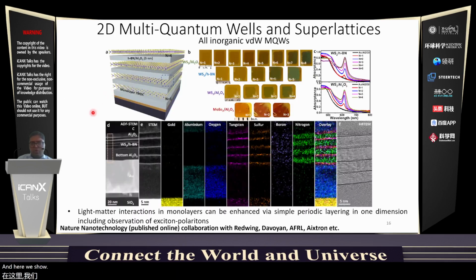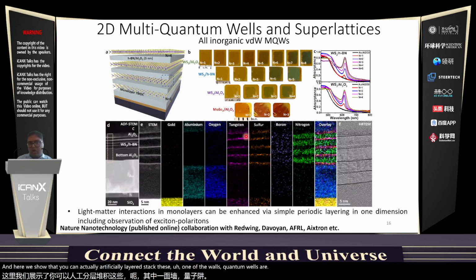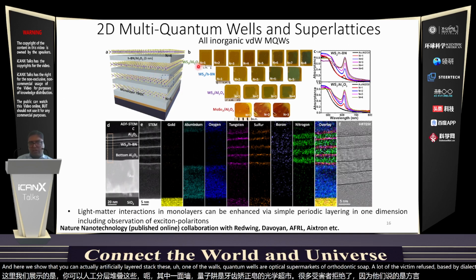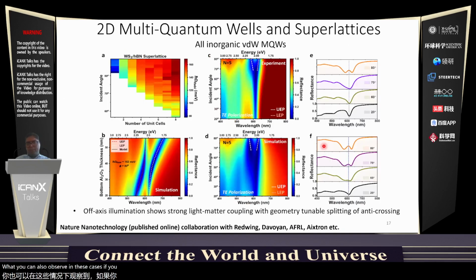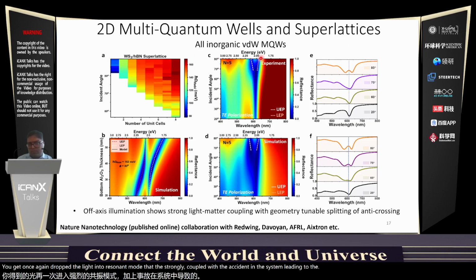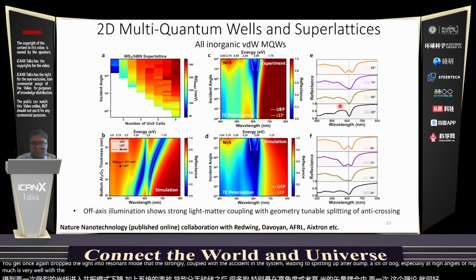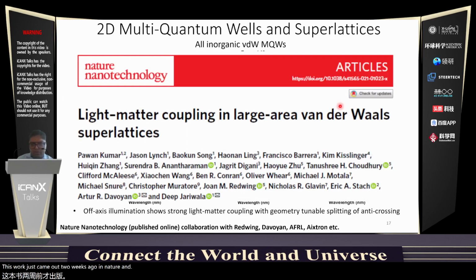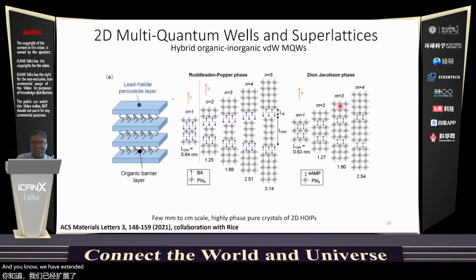And here we show that you can actually artificially layer and stack these van der Waals quantum wells or optical superlattices or excitonic superlattices with TMDC spaced by dielectrics such as alumina or hexagonal boron nitride. What you can also observe in these cases, if you couple light at an angle, you can once again trap the light into resonant modes that can strongly couple with the excitons in the system, leading to splitting of exciton polaritons, especially at high angles or high wave vectors of the light coupling inside. And once again, the theory matches very well with the experiments. This work just came out 2 weeks ago in Nature Nanotechnology.